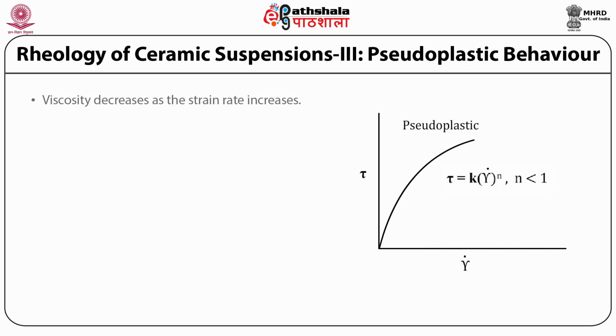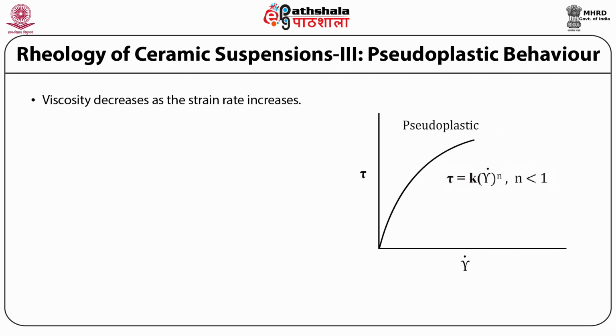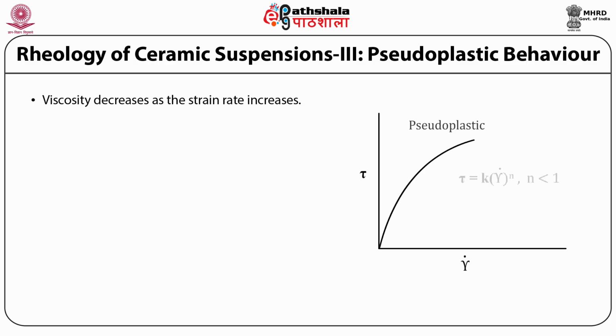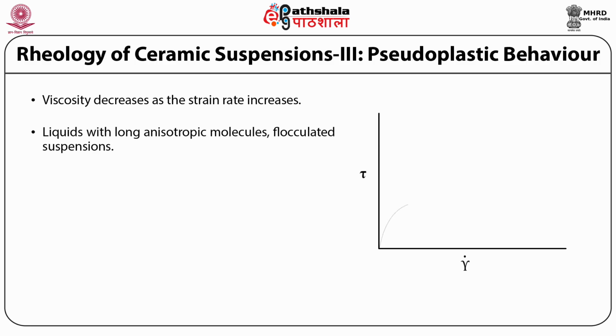In this case, the viscosity decreases with increasing strain rate, that is, the apparent viscosity, given as eta A, is equal to tau divided by gamma dot. So this apparent viscosity decreases as the strain rate increases. A plot of the strain rate versus stress has a decreasing slope with increasing strain rate as shown in this figure. This behavior is found in liquids with long anisotropic molecules, suspensions with long particles, and in flocculated suspensions.